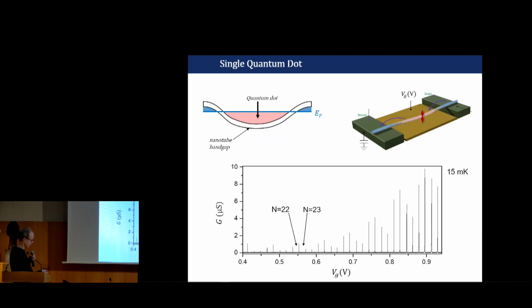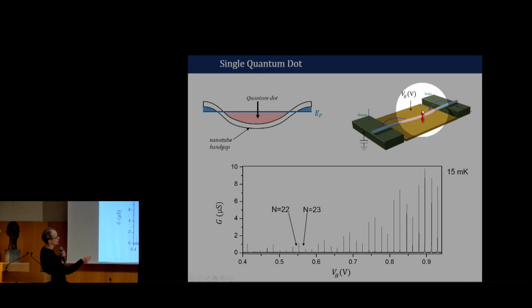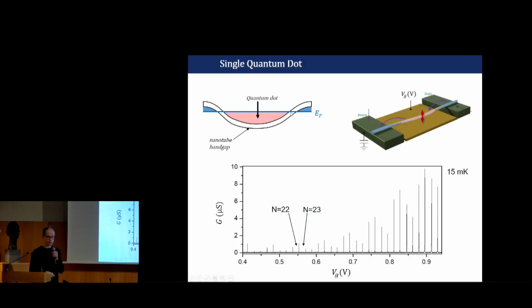So we are able to produce a quantum dot, here in the pink region. We have two tunnel barriers, and we get the quantum dot by applying a voltage on the gate here. When we apply a voltage on the gate, you see that we have a dot in pink that is electron doped, while here in the blue region, we have the electron reservoir, and you see it's p doped. So the tunnel barriers are formed by the p-n junctions when the Fermi energy crosses the band gap. This is the way we form the quantum dots, and we can precisely control the electron number.